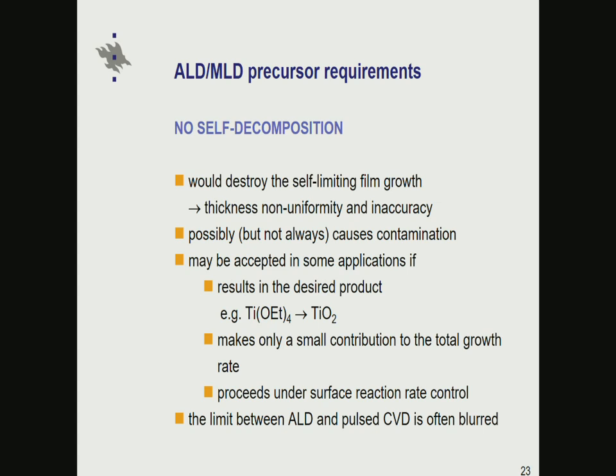Because in ALD, for example, if you are depositing oxides, you may use a precursor which is a little bit decomposing, leaving maybe some carbon there, but the next thing that happens is that you may have an ozone pulse coming over, and that will clean away a major part of these impurities. Sometimes the decomposition indeed leads into contamination, but not always.